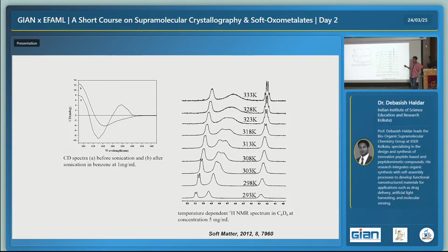And then we have studied this gel. This gel is actually forming on sonication. So if you have the compound, you dissolve it in the organic solvent, you heat it, you cool it, the gel probably does not form. But if you sonicate it, immediately the gel will form. We have studied by CD spectra how the sonication is affecting the backbone conformation for gel formation. What we believe is that in solution you have much more flexibility than in the crystal state. Though in the crystal the compound lost its C3 symmetry, in solution when we are sonicating it, the compound gets back its C3 symmetry, and then it helps to form the fibril structure, which helps the formation of the gel further.